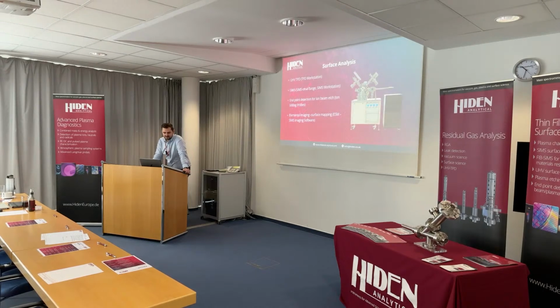For surface analysis, we have the TPD workstation, temperature programmed desorption, where we look at samples such as dissolved hydrogen or deuterium in steels. We heat up the sample and then measure the species coming off with our quadrupole mass spectrometers. We have SIMS, secondary ion mass spectrometry systems with integral ion beams to locally analyze surfaces. We work with ion beam etching systems, so we have ion milling probes as well. And we have custom software for elemental imaging and surface mapping.